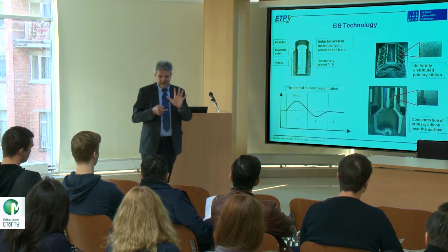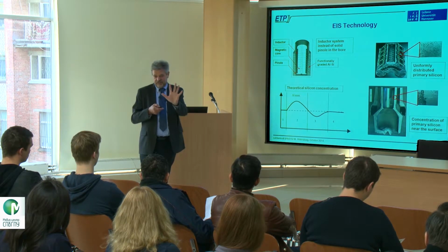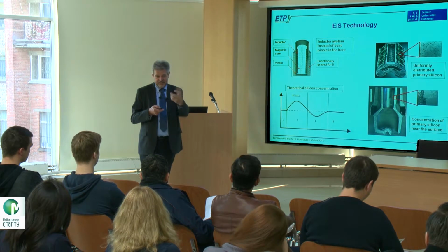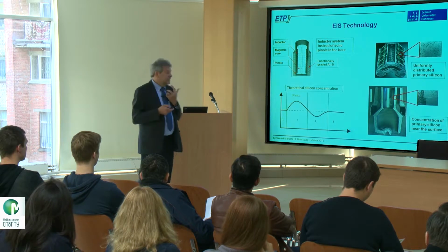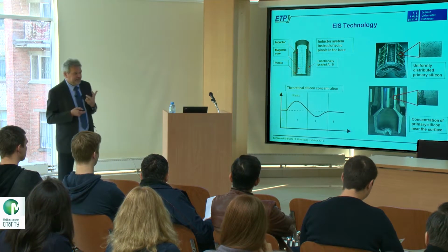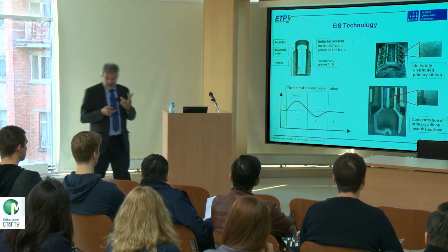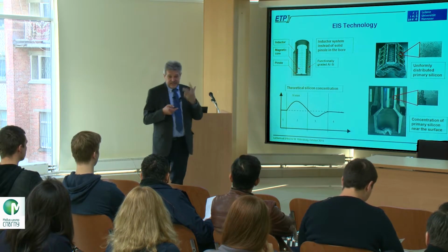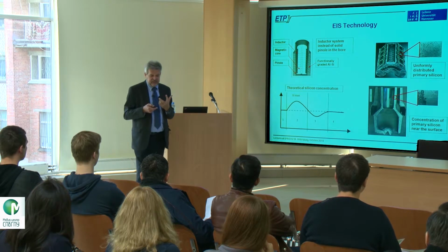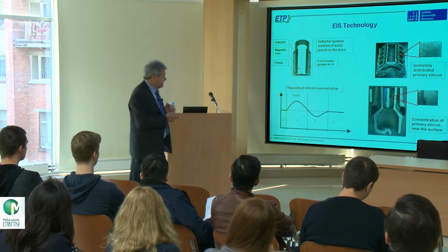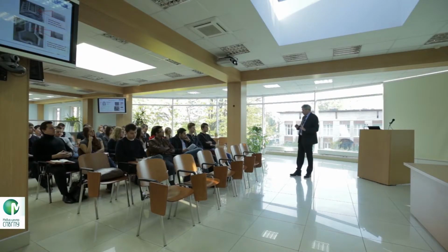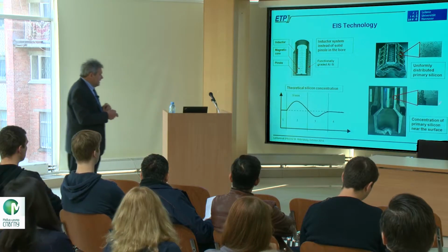So what happens inside the liquid? The aluminium is pressed away, but of course there can be no hole, because it's a liquid. The silicon is going to the surface. This is an effect very well known in EPM. It is called purification, or segregation. So you can really purify materials by using electromagnetic fields: all impurities, which are normally lower conductive, come to the surface. And this is used here.